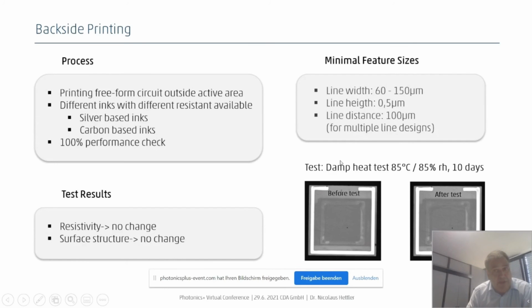And here I have also some information about the different feature sizes that are possible. So depending on the ink, the minimal line width is between 60 and 150 microns. The line height is usually in the range of 0.5 microns. And if you use designs that are using multiple lines, then the distance between the lines should be 100 micron.